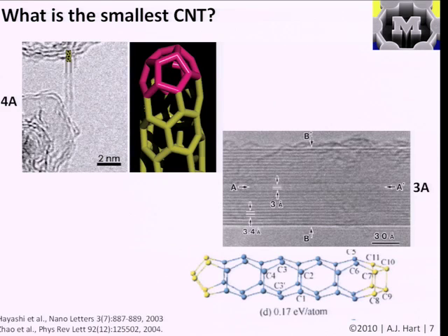Okay. So, it turns out that the smallest nanotubes, you don't necessarily have the hexagonal ring around from the top, but it's pretty close to that. I guess you get into the definition of when you start to break down the idea of rolling up a sheet. But what governs the stability of the smallest nanotube is the fact that you are introducing so much strain into the lattice to wrap it that it becomes highly unstable. And those answers of about 12 atoms or about 1 ring turn out to be close to correct, not necessarily because of that exact ring, but because you're distorting what wants to be a planar structure so much.